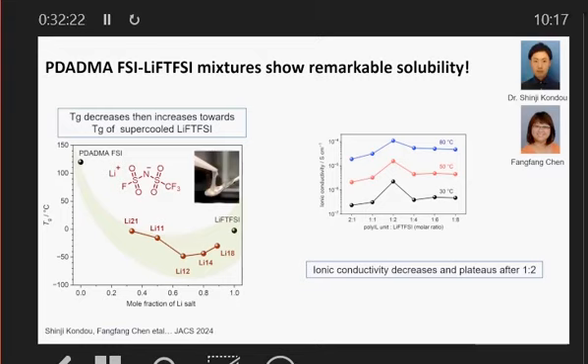It's got to be more than that. And I haven't got time to go into details here, but it goes back to whether or not the lithium ion is coupled or decoupled from the rest of the motion of the system, right? In the molten salt, it seems to be more coupled than it is in the polymer salt system. So this again goes back to this cage environment and how that changes, and the rate of change of the cage environment for a lithium ion. So that was interesting, disappointing, but interesting.